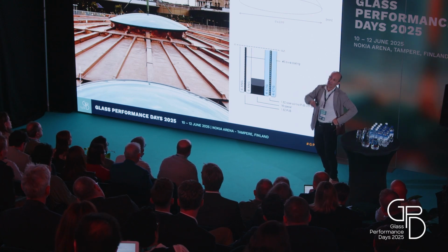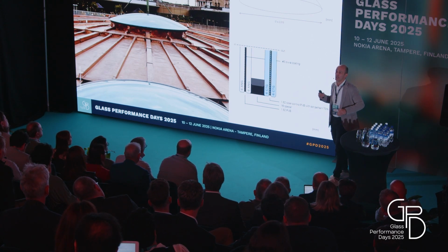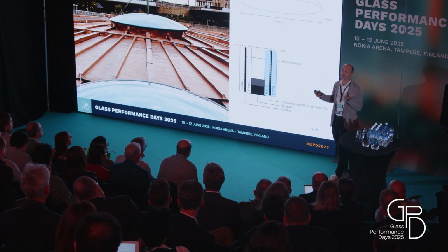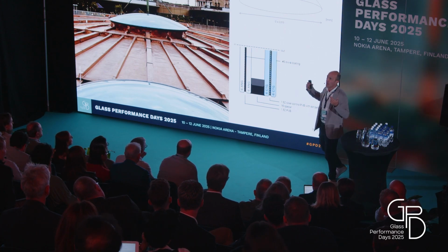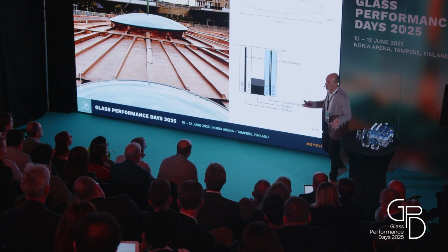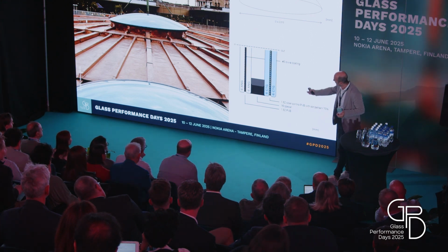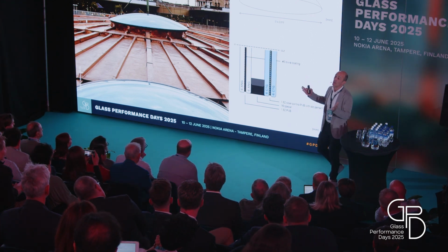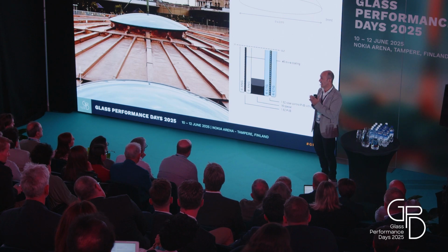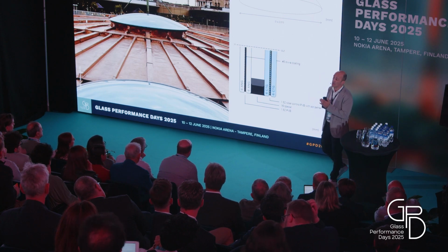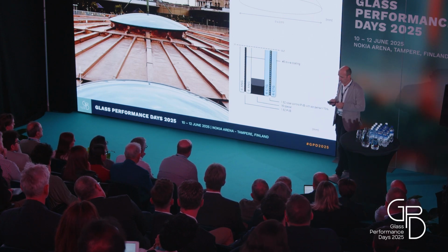Logically, one of the big disadvantages of chemical strengthening is that we cannot have anything on the surface. We cannot have a ceramic frit. We cannot have a Low-E or solar control coating. Nothing. So in this case, at the outer layer, we are sandwiching the solar control interlayer, and we are sandwiching a printed interlayer with a dot pattern.